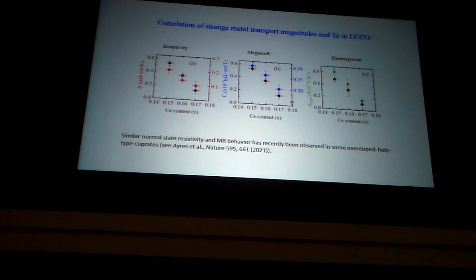All right, so here's an interesting result that's not understood that we found from our work on electron-doped cuprates, that the coefficient of the linear in T resistivity seems to scale with the TC. In other words, as TC goes down in this, what's called overdoped region, the coefficient of the linear term decreases. And also the coefficient of the magnetoresistive term decreases with doping, and the coefficient of the logarithmic thermopower decreases with doping. So as TC goes down, all three of these coefficients go down. So it looks like, in some way, there's some relation between whatever's causing these strange metal behaviors and the TC.